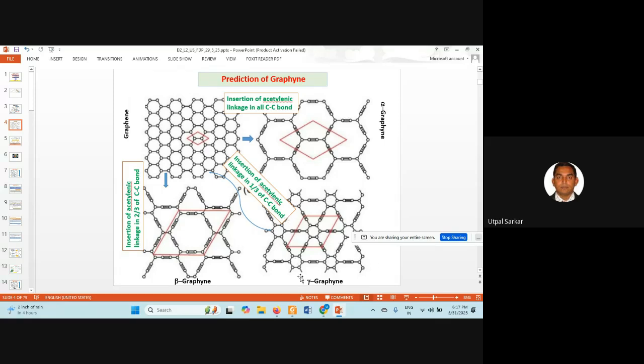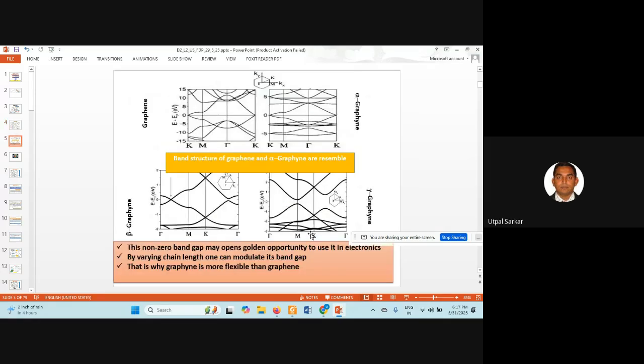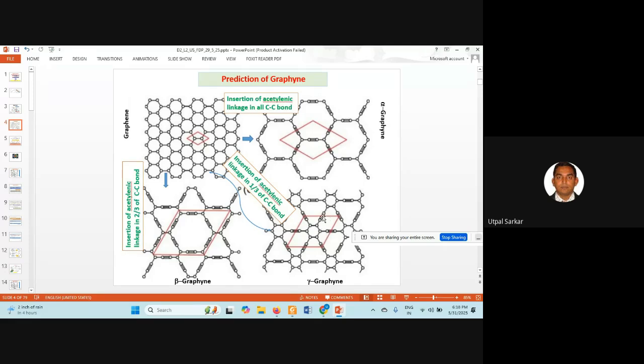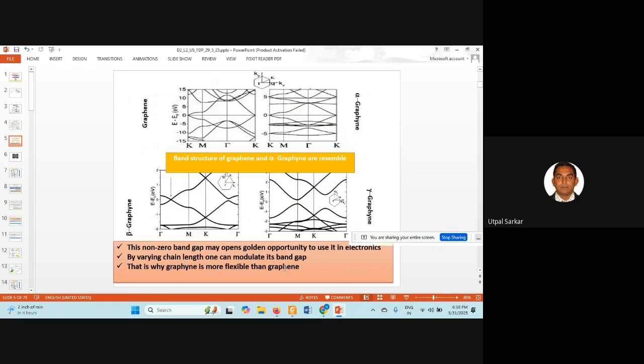So we will mainly focus on this gamma graphyne because it is showing an intrinsic band gap and can be used as a semiconductor. This is the band structure of graphene, and you see the Dirac-like cone here, so it does not show any band gap. Alpha graphyne is also the same, beta graphyne also the same, no band gap. However, in the case of gamma graphyne, you are seeing a band gap opening at the end point. This non-zero band gap may open a golden opportunity to use it in electronics, and by varying the chain length, here at this position, one acetylene linkage, two acetylene linkages, three acetylene linkages, you can modulate the band gap of this system, and that's why graphyne is more flexible than graphene.